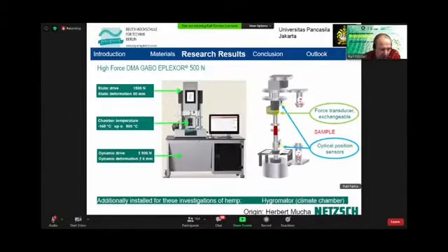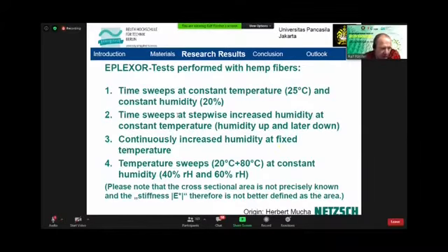biomaterials for new applications. Here are some tests which we have carried out with hemp fiber. We have a constant temperature of 25 degrees and a constant humidity of 20%, and with a time sweep which increased the humidity stepwise, and the temperature sweeps between 20 and 80 degrees at two constant humidity values of 40% humidity and 60% humidity.